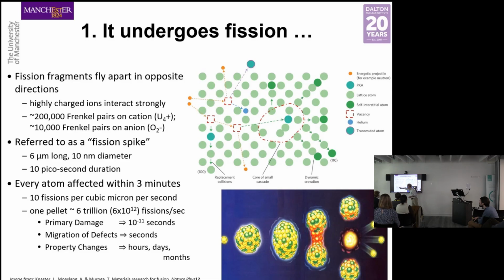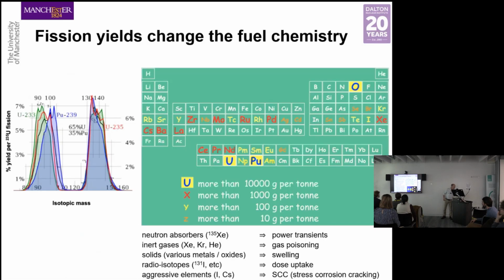There are around about 10 fission events in every cubic micron every second in the core of a reactor. There's a lot going on. In a single pellet, there's about 6 trillion fissions per second. They produce primary damage that occurs of the order of femtoseconds, migration of defects that occurs over time periods typically of seconds, and the property changes that result from these nuclear events can take hours or days or even months to manifest themselves. But there's a range of time frames, but the events itself are affecting pretty much every single atom within the core of a reactor, and they do so in an incredibly short period of time.